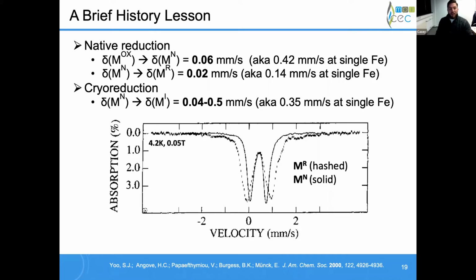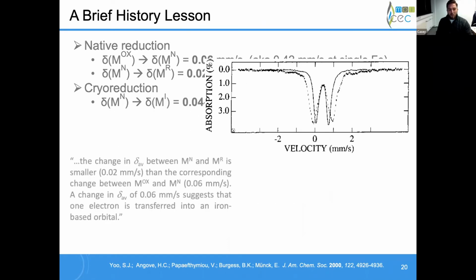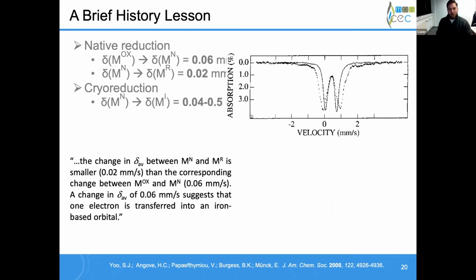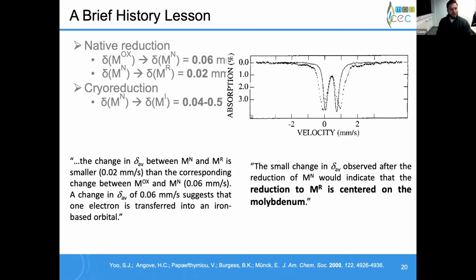In cryoreduction, they had a very similar shift, and from that, they concluded that when you cryoreduce your sample, it looks like you have an iron-centered reduction, and when you put it under native turnover, it does not look like an iron-centered reduction. And so as a negative result, it was proposed that molybdenum was the center for reduction. And this didn't seem exceptionally unusual because at this time, molybdenum in FeMoco was believed to be molybdenum 4. And actually the De Beer group since then has demonstrated very well that molybdenum in FeMoco is molybdenum 3.